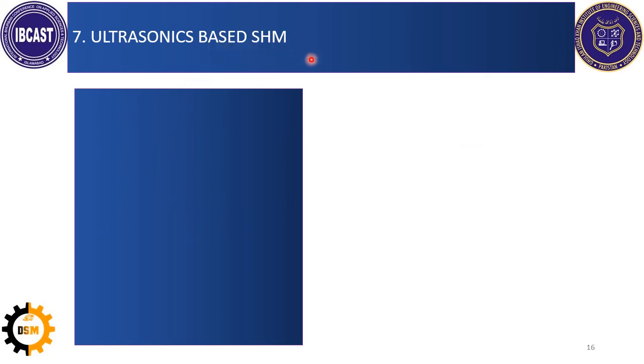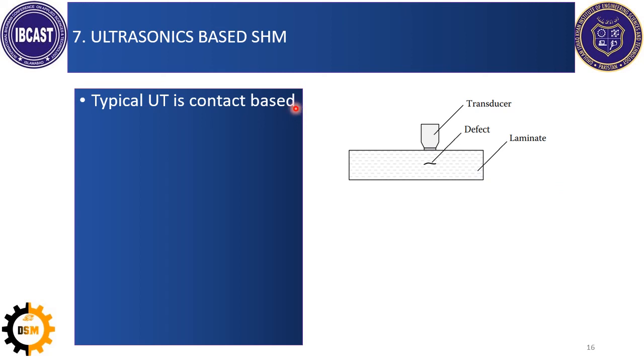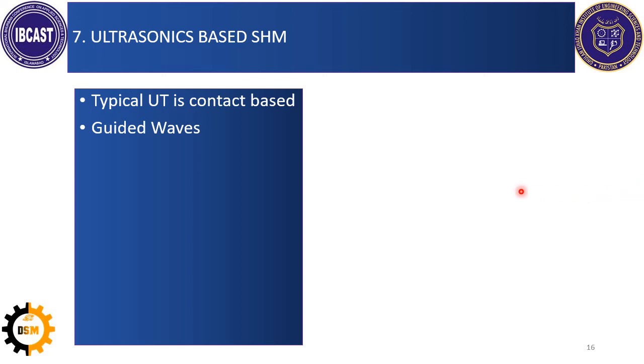Ultrasonic based structural health monitoring is the most common one. Typical ultrasonic testing works with a contact based transducer which detects the defect, but new ultrasonic methods are non-contact based. Basically, guided waves are low frequency waves transmitted through large surfaces, and these waves can be detected using non-contact methods. Another way of ultrasonic testing is bulk waves, which are high frequency complex waves which attenuate very fast. Guided waves are good for long structures. Bulk waves are good for complex structures and short attenuating surfaces.